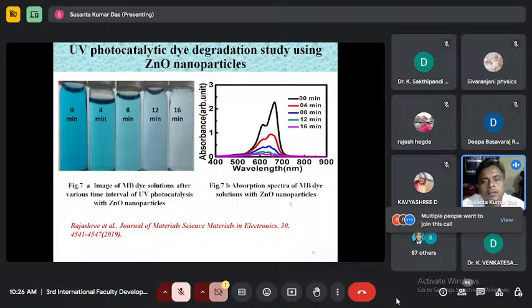And you can see we found that within 16 minutes we can completely decompose the dye, which was also clear from the absorption study. This was a low cost experiment, and it was published in a very good journal, Journal of Materials Science: Materials in Electronics, and it has been cited more than 20 times, I think, at this point of time.